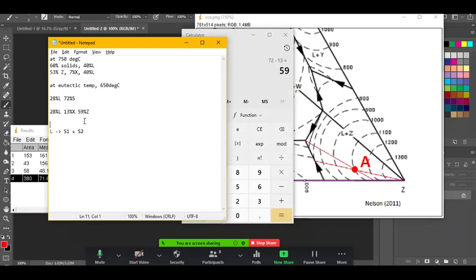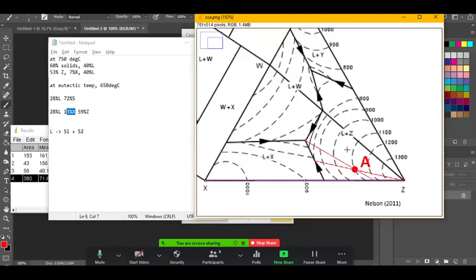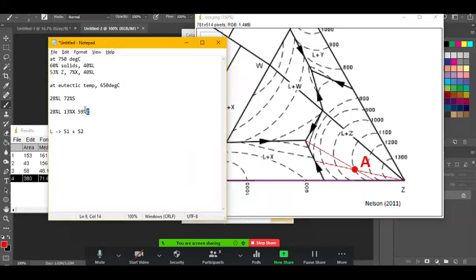At any point in time, I can measure, say, this X, 13% X, or rather the liquid, because the liquid is what I can actually measure. This Z and X is always 100%, right? Because the ends of their tie lines are always at this vertex, which signifies 100% Z, and this one, 100% X. Therefore all of these will always be 100% Z and 100% X component.